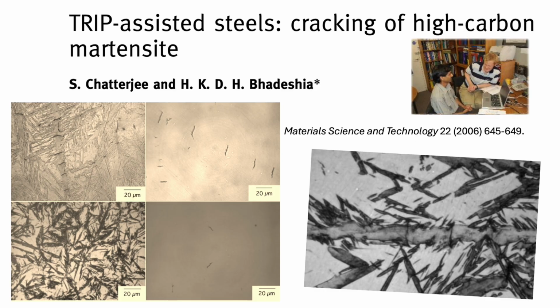That's a great way to put it. Load transfer becomes really difficult when the hard phase, the martensite plate in this case, is very, very small relative to the surrounding softer matrix. The stress required for fracture just can't build up within that tiny plate. So the martensite in TRIP steels is brittle, but it's formed in such tiny pieces that it doesn't get the chance to crack. Essentially, yes. The surrounding steel matrix can deform around it, triggering the transformation, but it can't load up those tiny martensite islands enough to break them. Okay, that makes sense.